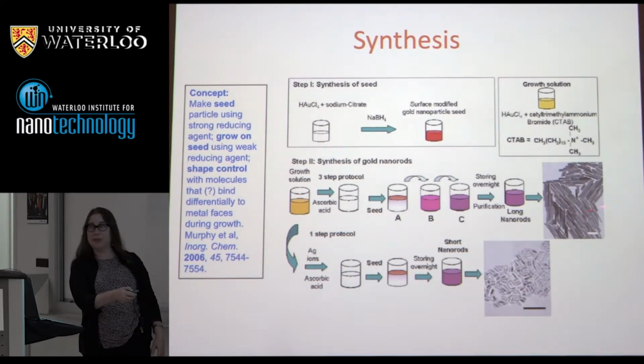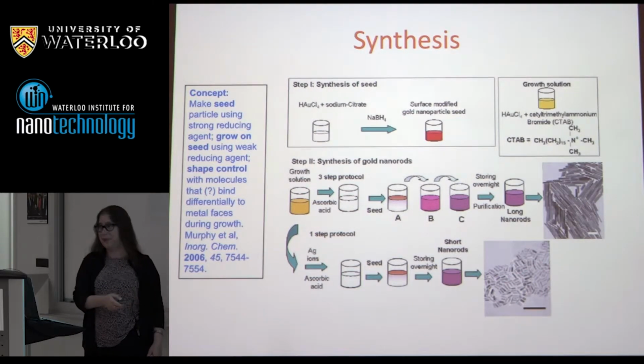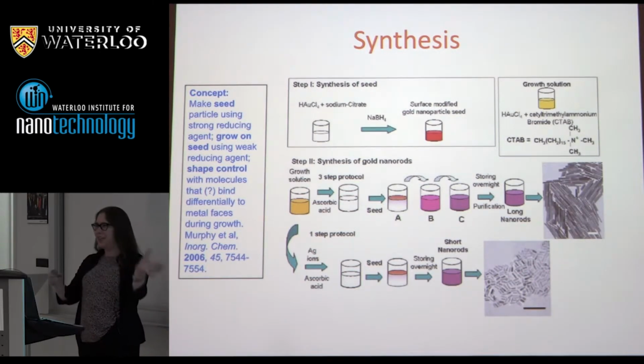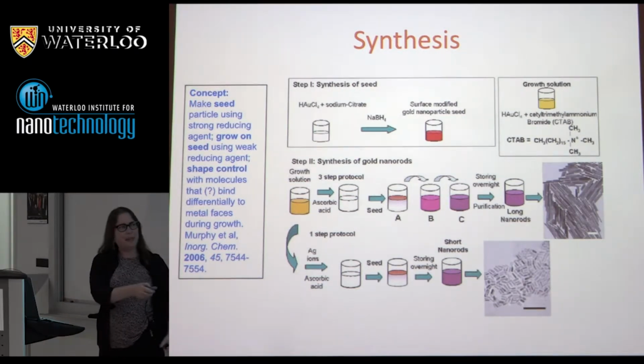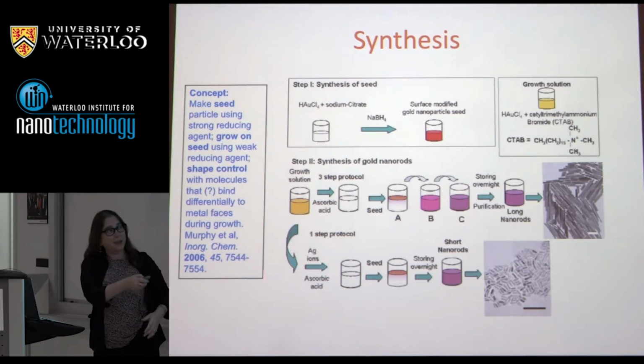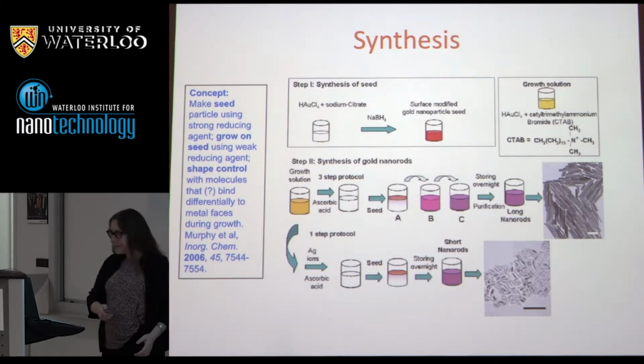That was a heavily purified micrograph. This is a completely unpurified micrograph. So your spherical side issue is gone, but now you have a whole bunch of rods, which is good, but now you can't really grow them any longer. You have to go back to the beginning, add a different amount of silver. Okay, so as you can imagine, we spend a lot of time doing all kinds of chemistry in here, which I will skip for the most part.